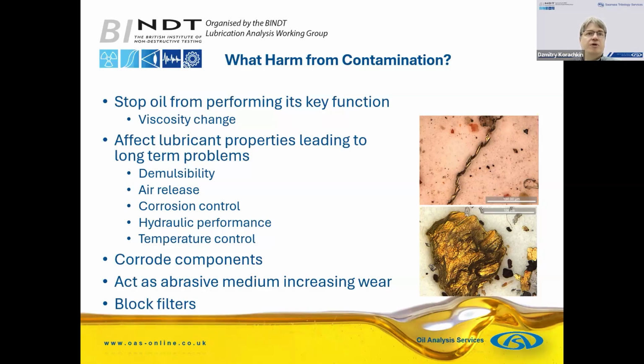And there are other functions that can be affected, things like demulsibility, the ability for the lubricant to separate from water, and air release. There'll be issues with corrosion control, hydraulic performance, temperature control. Contaminants can corrode components, and a lot of the time when we talk about contaminants, we also mean particles, where debris becomes a contaminant itself once it's generated. So those can act as an abrasive medium, increasing wear.